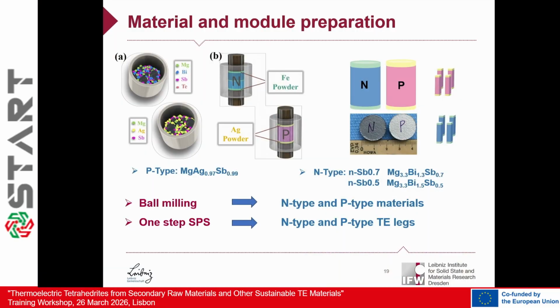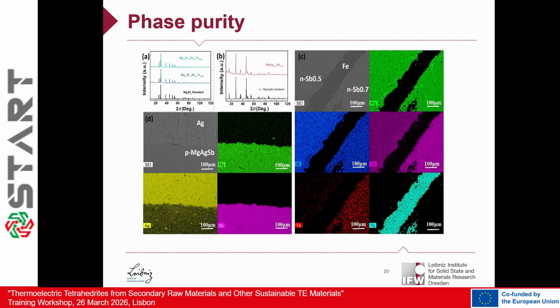Also, in order to simplify the contacting, we directly compact the contact materials together with the thermoelectric material. For the magnesium silver antimonide, we use silver as a contact material, and for the N-type material, we use iron as a contact material. Here is just an impression of how these contacts look. We have, for example, the transition between silver and magnesium silver antimonide. There's a quite nice interface, and no large intermixing zone. The same holds for the N-type material with the iron: we also have a good transition between both materials.